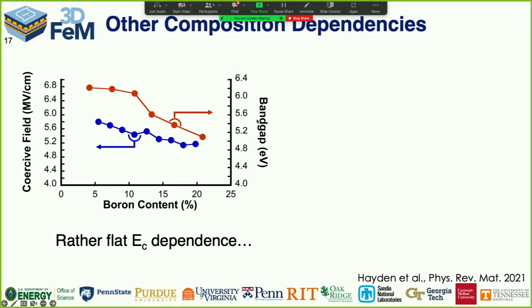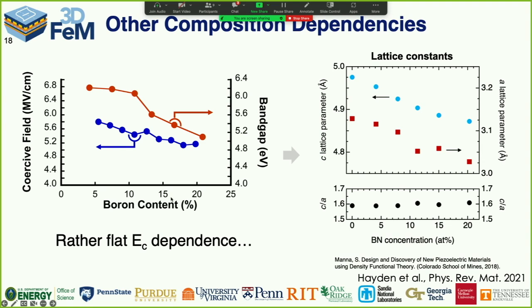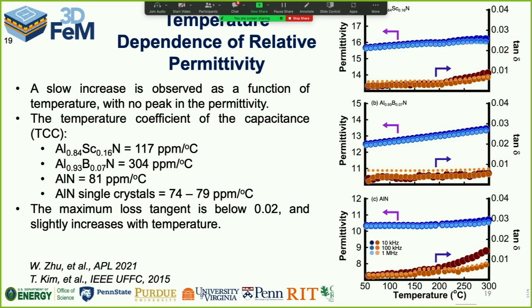So this shows the composition dependence of the coercive fields and the band gap. As we add boron, the band gaps stay nice and high. So we start at about 6.2 electron volts, and we only drop to just about 5 at the limit of the boron solubility. The coercive fields don't vary as much as I was really hoping; I hoped this would plummet, but it doesn't. Nature didn't give us that. And part of the reason it doesn't is that it turns out that the boron doesn't do what we projected. It doesn't flatten the tetrahedra very well. And as a result, we don't change the crystallographic C by A ratio very much at all as we add boron into it. It's a totally different mechanism from aluminum scandium nitride. That's fun. We're still trying to figure it out.